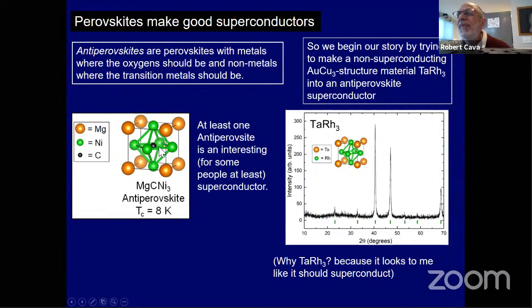So the whole story here is that you want an electropositive element to put here, an electronegative element to put here, and then a small element to put in the hole. In this case, it's carbon. So a typical thing to put in a hole could be carbon or boron or beryllium. We don't work with beryllium, but carbon or boron or nitrogen could go in a hole. And a typical electropositive element would be like magnesium or rare earth or something like that.